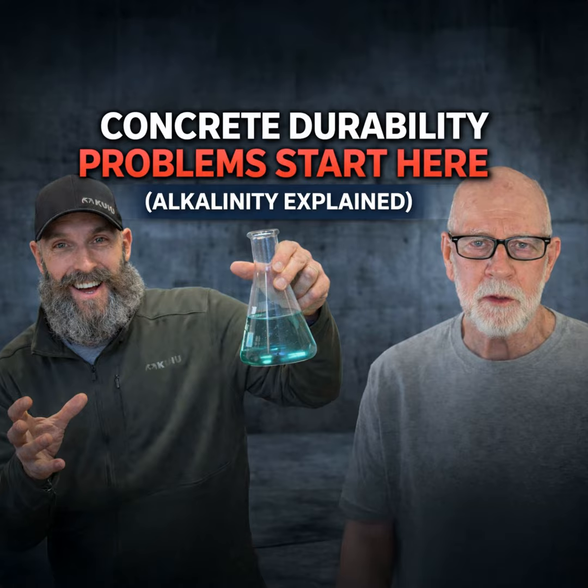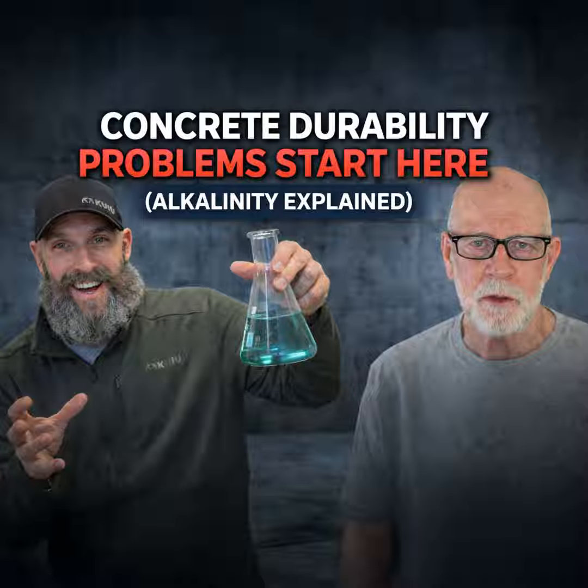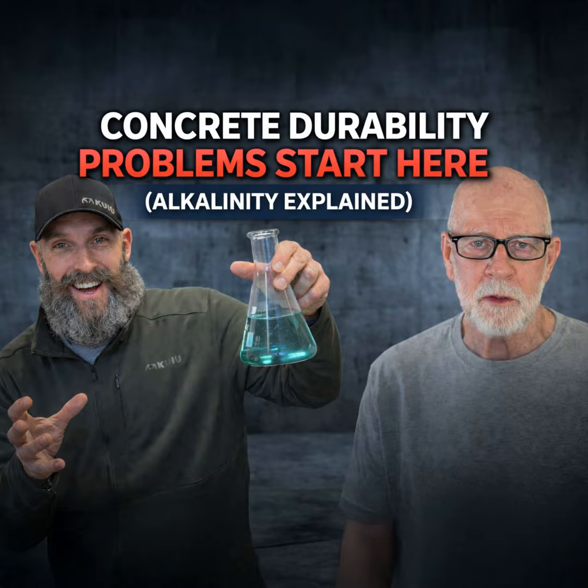Yeah, but again, they don't think outside the box. They look at that, it's protected. Well, yeah, for the time being, but at what cost? Because if you look at ASR for floors, ASR can get triggered by the application of an epoxy resin. Whereas if you left it alone, the ASR wouldn't trigger, because ASR needs alkaline and moisture and a medium, which is your amorphous aggregate, to create ASR. But if you don't trap the water in there, there's generally not enough to trigger the reaction, unless it's like a polished surface, a dense surface.